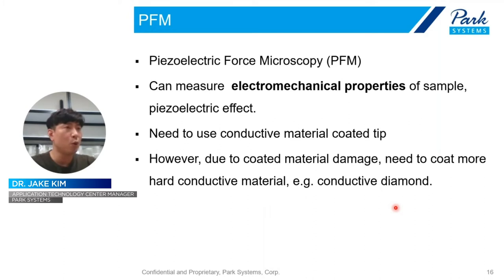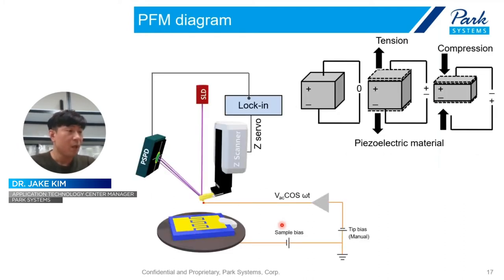Of course, we can use a gold coated tip, but due to the contact mode, that gold coated layer can be easily disappeared or damaged. So we recommend a conductive diamond or hard conductive material coated tip. Briefly, this is a simple diagram of PFM. The AFM tip contacts the sample and we apply the bias, then if the sample has a piezoelectric property, we can monitor this PFM signal.